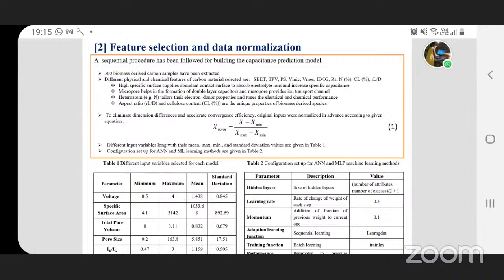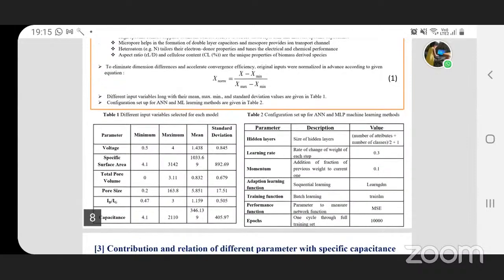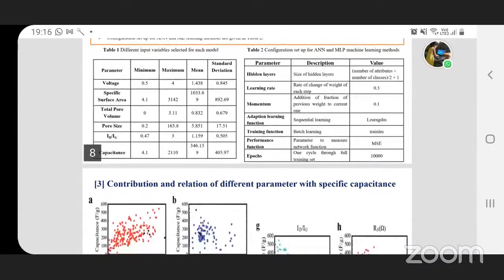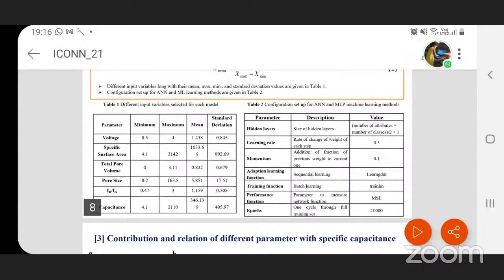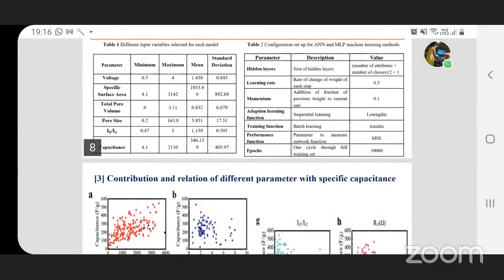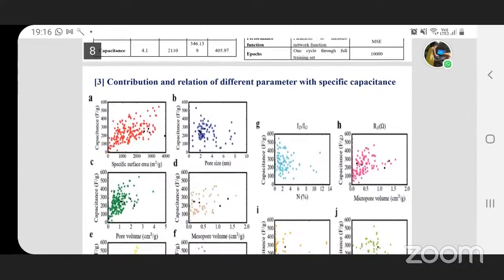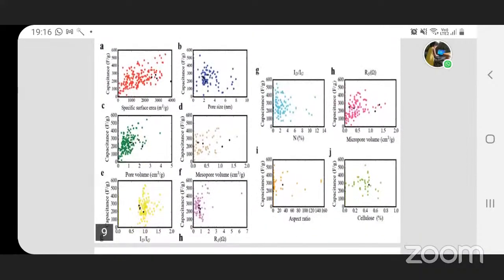As we can see, there are various reasons associated with the selection of parameters. For example, the micropore helps in the formation of the double layer, whereas the mesopore helps in the ion transport channel. So we have considered these two pore volumes separately, and aspect ratio and cellulose content are unique features of the biomass-derived species. For the dimension differences and conversion efficiency, first we have normalized all the values, and the different parameters selected along with the minimum, maximum, mean, and standard deviation values are tabulated in table 1, whereas table 2 provides the different configuration setup for ANN as well as machine learning methods that I'm going to share next. So first, we have considered the different performance parameters which are going to affect the specific capacitance.